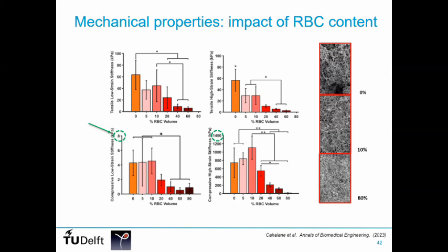And that seems to happen at a certain porosity of the network. If we increase the density of the network, that feature disappears. I'm fully aware that these images are not the best, but believe me, this is what happened there. So maybe that's one of the explanations for this increase in stiffness, that these red blood cells were forced into a different shape in the network.